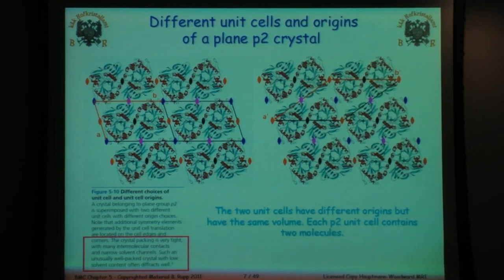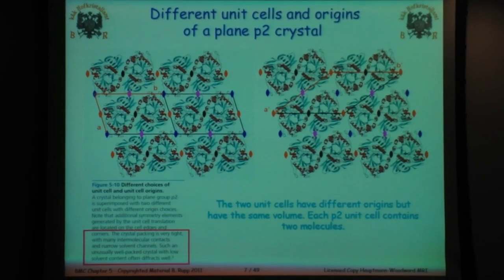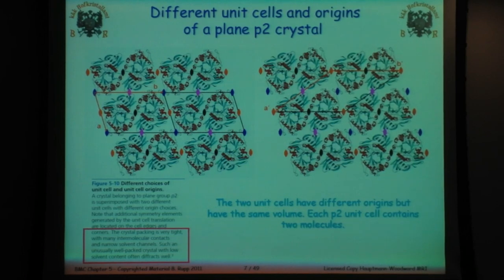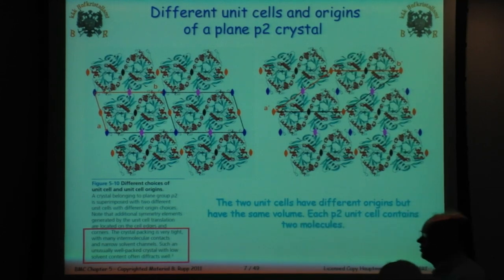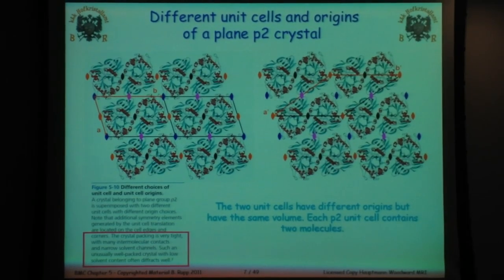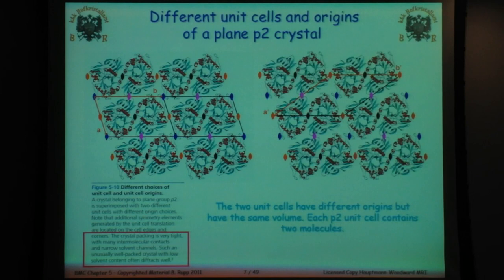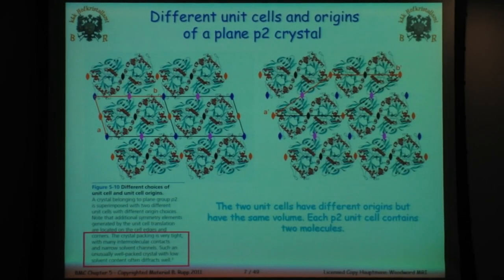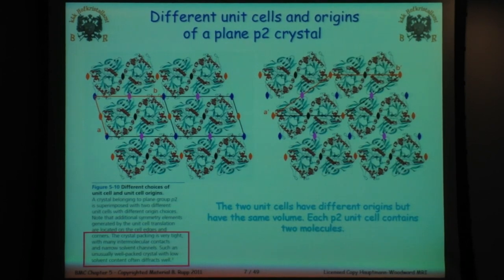This also shows that the crystal packing is tight, so this is a real structure. This probably has a low solvent content because there's not much room for water. Crystals with low solvent content often diffract very well. When you're doing crystallization screening, it makes a lot of sense to try different crystals and see if you get a space group with low water content that diffracts at high resolution. Sometimes when you have symmetry present, you may have an active site that's blocked — another crystallization condition may leave that active site open, which matters for ligand binding studies.